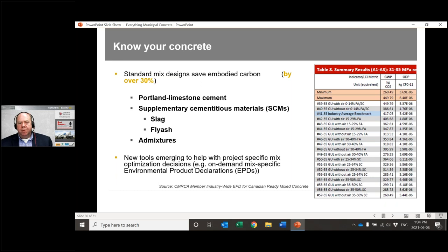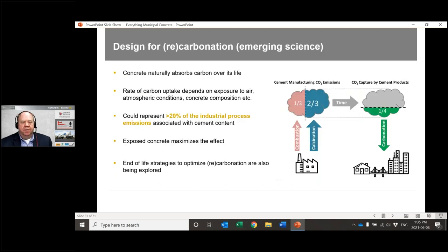How do we reduce that carbon footprint? We start implementing other technologies like Portland limestone cement, get a 10% reduction from that. And then we can start looking at supplementary cementing materials like slag and fly ash. There's also new chemical admixtures coming out again, for optimizing mix designs to reduce carbon impacts. So there's a lot of things that we can do. And there's a lot of pressure for the industry to move to environmental product declarations that clearly identify what the CO2 is.